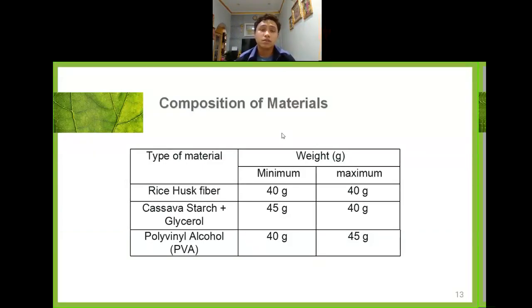And then we go to the condition of the sample. Measurement of the sample is necessary in order to have a precise composition of the material to be filled inside the mold. The raw materials are prepared to be filled with approximate mold size. The first one is rice fiber. I use the rice fiber, and then cassava starch and polyvinyl alcohol, which is PVA.